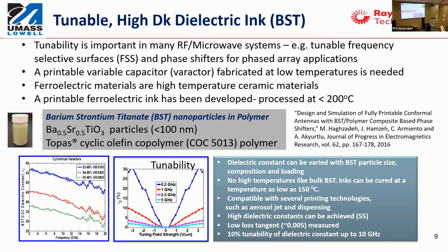So instead we made a BST ink utilizing BST nanoparticles. And we can vary the dielectric constant, the real part, anywhere from like 6 up to 50. So it can be used not only as a ferroelectric ink, but also as a high K ink, for antenna miniaturization and things like that. We've also demonstrated tunability at 10 gigahertz, somewhere between 10 to 12%. And our losses are within the 10 to the -3 regime up to about 12 gigahertz.